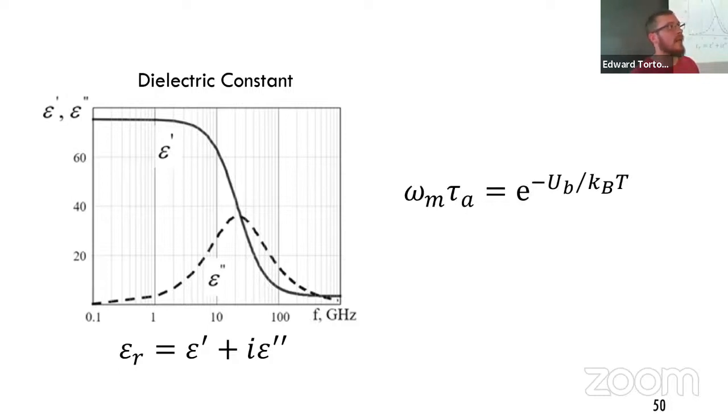And so that is a future experiment, in terms of trying to essentially saturate the system, getting all the dipoles to line up, and then increasing the field more and more and seeing that it's not changing the dielectric constant, or it's not changing the voltage. And so, yeah, there are definitely more experiments in terms of proving that this thing is ferroelectric, but right now we're really more studying the molecules inside and their dynamics inside the crystal.